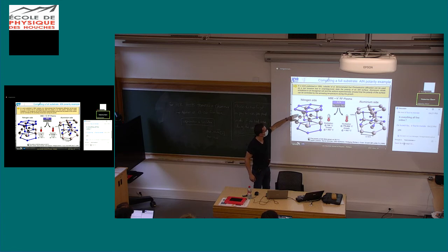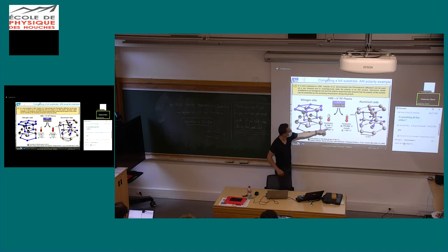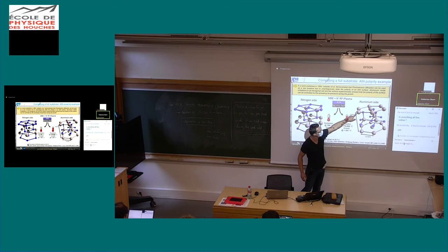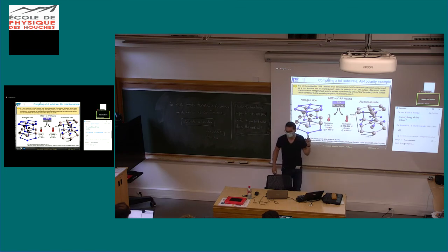So in this case, the surface is nitrogen terminated, and the tetrahedra are pointing downward. And in the other polarity, if the nucleation temperature of the growth is higher, but the growth temperature is the same after, they were able to promote the aluminum side with tetrahedra pointing upward, okay?